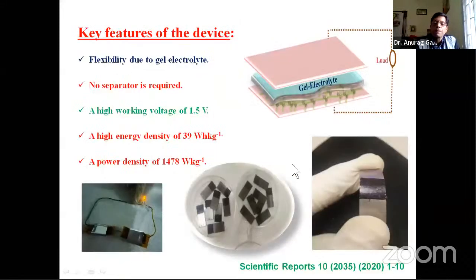So the key features of this device: first, it is flexible in nature. You can fold it into different shapes. Second, no separator is required, because the gel electrolyte itself works as a separator, since separators are also polymer materials. So you don't need to put a separator separately. And the energy density is quite good, 39 watt-hour per kilogram, and the power density is already high, 1478 watt per kilogram. So this is the approach of making such supercapacitors.